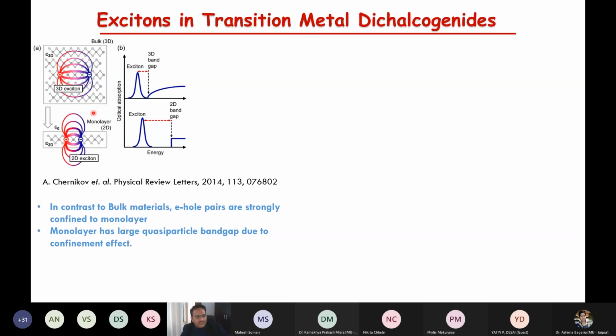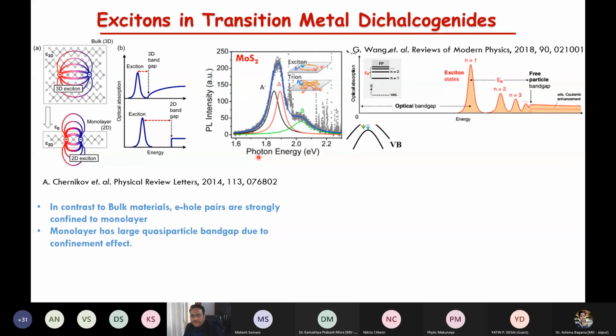Coulombic interaction. But if you confine them in a monolayer, okay, which means you call them 2D excitons, and they are very, very interesting because now the continuous spectrum here has a gap here. Okay, so this is the excitonic energy here, optical absorption, and then you have a gap here. This is coming because of the confinement of the charge carriers, and this gives rise to a very, very interesting aspect of the physics.